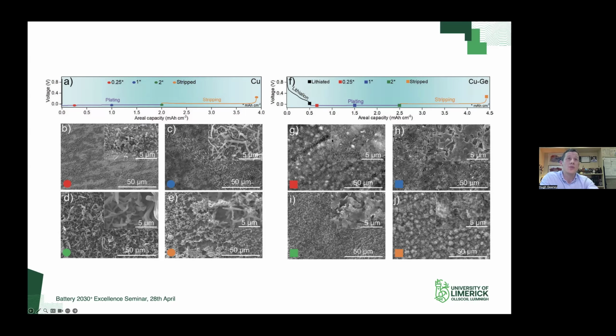When we compare that then to the germanium scenario here on the right-hand side, what you'll see first is you have this initial lithiation. So that is lithiation of the germanium nanowires. This is with an additional 0.25 milliamp hour per centimeter squared capacity. This is with one, this is with two, and this is with it fully stripped out. So if we compare these directly, so let's say if we compare H to C, you can see that we've really regulated that plating morphology compared to the standard copper. And by the time we get to 2, we've really held back that anisotropic lithium plating characteristic. With J here, I just want to highlight that this is not residual lithium. What this is is the starting out germanium nanowires. And if you look at the electrochemical profile that you have here, we have basically only slightly delithiated that.